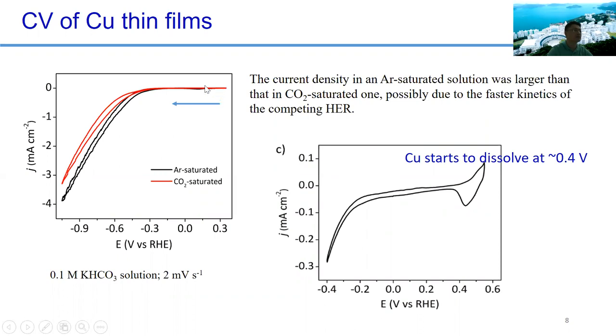We can scan the voltage from positive to negative to initiate the carbon dioxide reduction. The black curve is in argon saturated bicarbonate solution, and the red one is with carbon dioxide. With argon saturated solution, we can see the current density at the same voltage is actually higher than in carbon dioxide saturated. This is because during the carbon dioxide reduction, it generates some reaction intermediates or byproducts that cover the surface. So the current generated from the chemical reaction is actually smaller in carbon dioxide, because in argon saturated, the main reaction will be the hydrogen evolution.